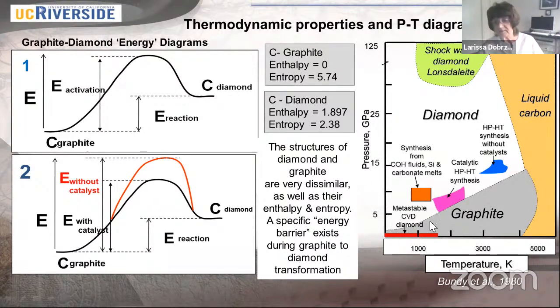The white field is where diamond is stable, and the yellow field is where carbon exists only as liquid carbon. It's very high temperature, more than 4,000 K. And the gray field is the stability field of graphite. We see here that graphite can exist from low pressure and low temperature towards higher pressure, about 12 GPa, at a temperature of 4,000 K.